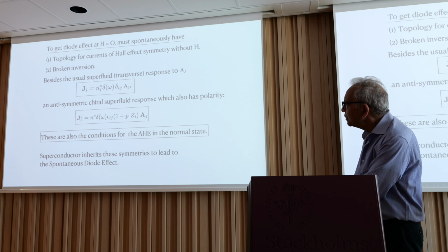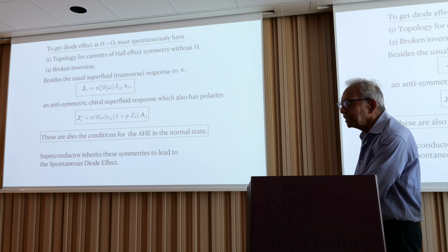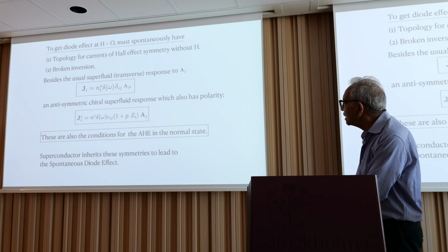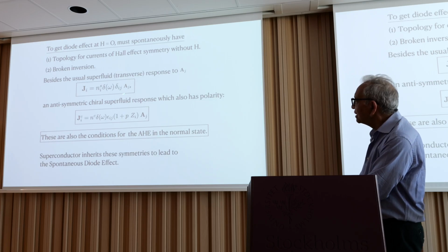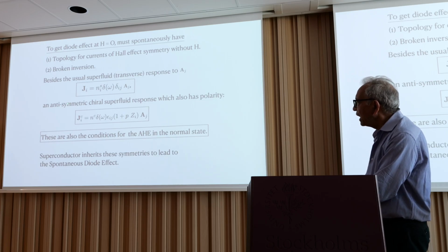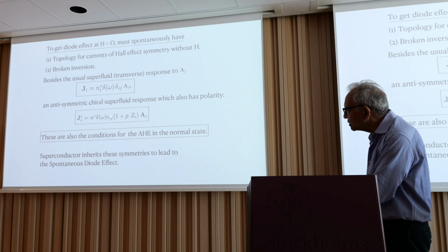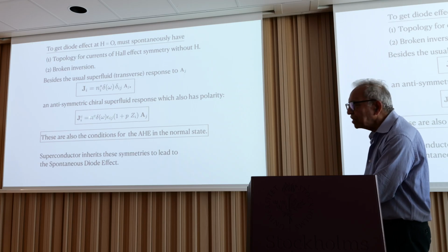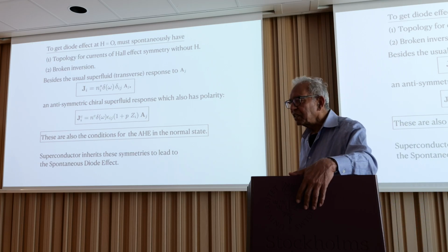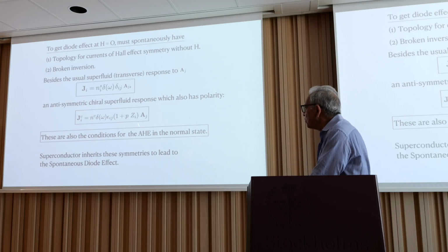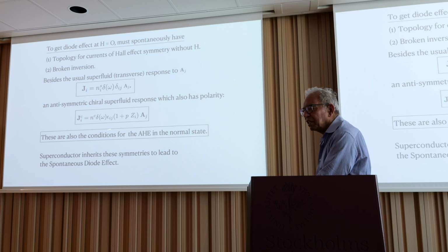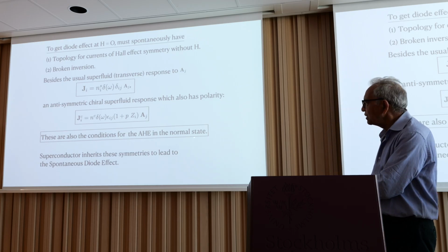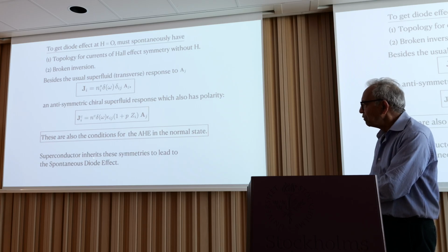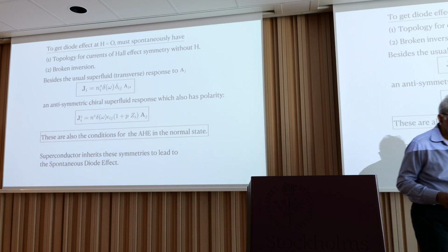So there's a superfluid density which depends on the direction of the principal axis, and it's diagonal. You also require an antisymmetric chiral superfluid response. So this epsilon ij. You need your superfluid tensor to become chiral and antisymmetric, and also it must be polar. It must break some reflection symmetries. So these are also the conditions for the anomalous Hall effect in the normal state. And the superconductor, if these happen in the normal state, must inherit these symmetries to lead to the spontaneous diode effect.